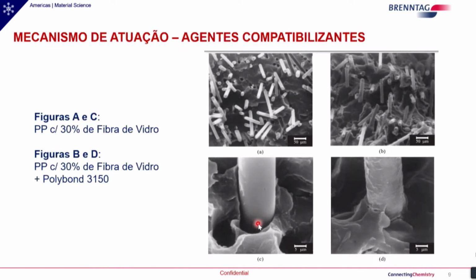We don't see an interesting interaction between the materials. And there isn't an interaction indeed. Well, let's just see what happens when we do use the compatibilizing agent. That's what we see on image B. We don't have the same density of void spaces in the structure of the composite. And right here on image D, which is an excellent image, it shows precisely what we were speaking about before, which is the wet, quote-unquote, polypropylene in the glass fiber.